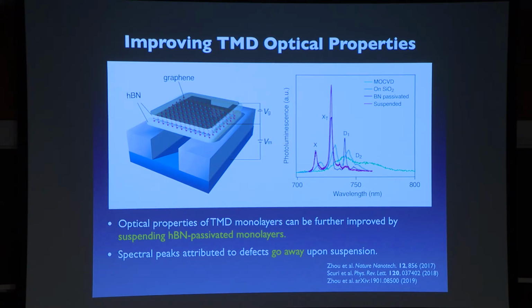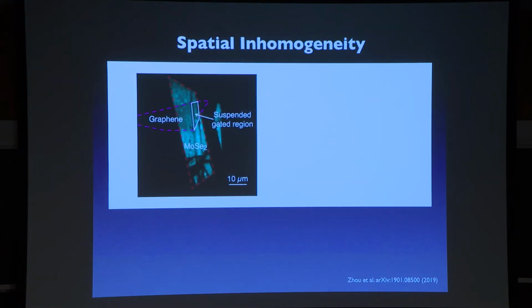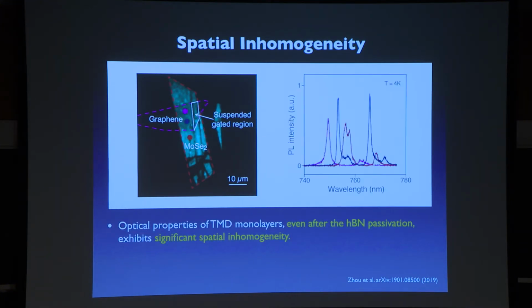And most importantly, the following happens. If you put these atomically thin semiconductors on top of a substrate, in this particular case regular silicon dioxide on a silicon wafer, then depending on where you measure the spectrum, spectral positions change quite a bit. That comes about because silicon wafers, however nice they are, have silicon oxide that holds different amounts of charges at different places, and that leads to this spectral position shift.